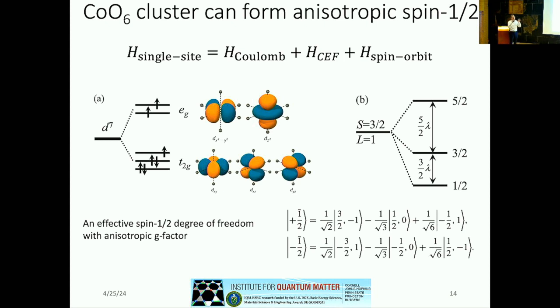So now I want to talk about how we realize this kind of Ising model at all. Because what I'd spoken about previously was an isotropic spin one half degree of freedom. Now I need something which is almost like a scalar degree of freedom, but with its inevitable quantum fluctuations. That turns out to be possible by using cobalt instead of copper, because cobalt has a 3d7 electron configuration, and that builds some orbital angular momentum into the ground state.